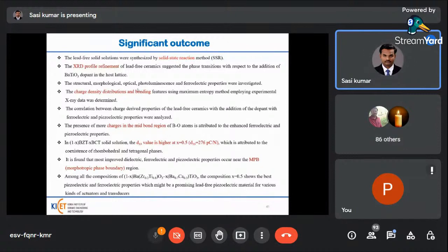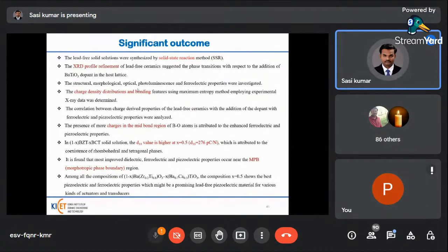And then the presence of covalency in the B-O atoms is mainly used to enhance the ferroelectric and piezoelectric properties. Among the different lead-free piezoelectrics, the BZT-BCT x equal to 0.5 composition has a higher d33 value, which is mainly attributed to the coexistence of rhombohedral and tetragonal phases in one composition, and it is found that the most improved dielectric, ferroelectric, and piezoelectric properties occur near the MPB, the morphotropic phase boundary region.